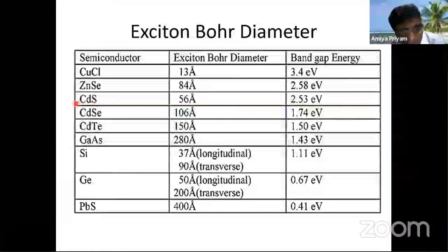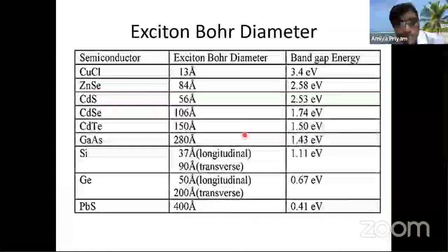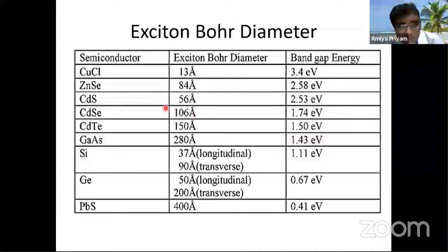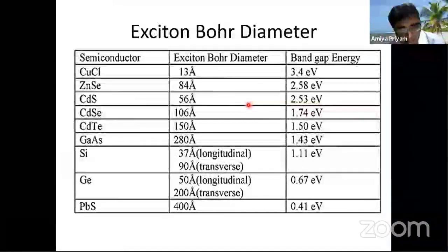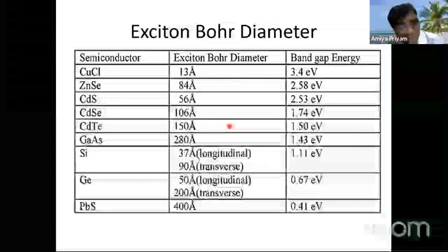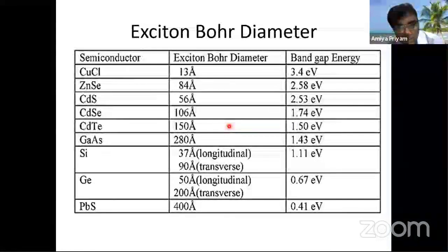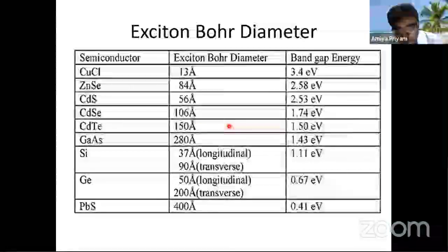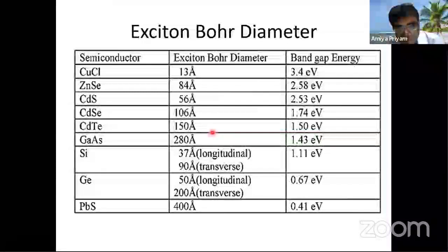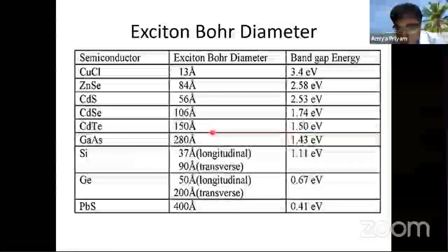The bulk cadmium sulfide is not fluorescent, but when you reduce it to such a small size, for cadmium sulfide, below 5 nanometers, then you see that they become fluorescent. They emit light on excitation with photons. They also show the electroluminescence property. Electroluminescence is also important because that is what we use for making LEDs: electric current is passed, and that excites the electron, and the relaxation process gives us the light.